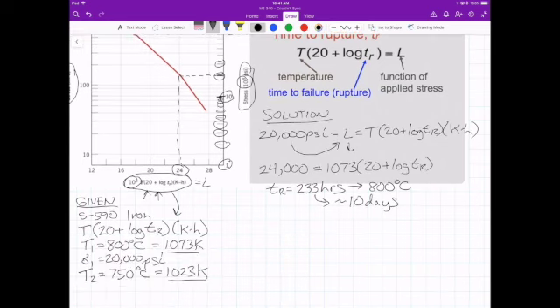What happens if we drop the temperature? We're not dropping it very much, just 50 degrees. We're going down to 1023 Kelvin. The equation's the same, 20 plus the log of TR. We're applying the same stress, so our L value is still 24,000.